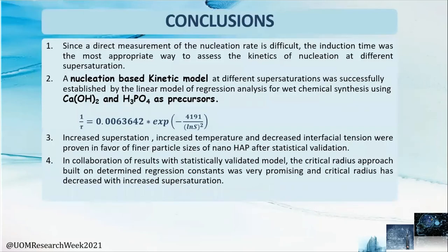In the conclusion, since direct measurement is not possible for nucleation rate calculation, induction time was a good indirect measurement. The nucleation-based kinetic model at different supersaturation levels was successfully established by the linear regression model. Increased supersaturation, increased temperature, and decreased interfacial tension were proven to favor finer nano-hydroxyapatite particle sizes. In collaboration with results from the statistically validated model, the critical radius approach was very successful in explaining the experimental results.